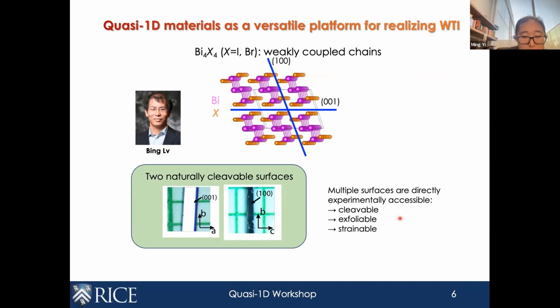And so our collaborator Bing Lv's group have very nicely grown these beautiful large single crystals. You can see these are single crystals of bismuth iodide, and they have very shiny and flat large surfaces, both on the top 001 surface and also on the side 100, which means that we can glue the samples with different orientations and then cleave them to expose large measurable surfaces with just standard regular ARPES with, say, a beam spot of 50 microns or so.